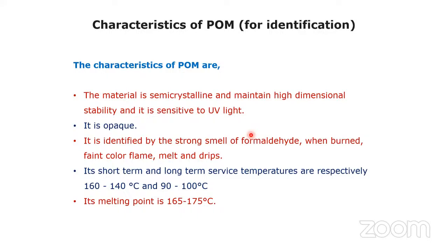Its short-term and long-term service temperatures are respectively 160 to 140 degrees Celsius and 90 to 100 degrees Celsius. Whatever the application temperatures, we can use it up to 160 for short term, and for long-term use you can use it at 100 degrees Celsius as well. Its melting point is nearly 165 to 175 degrees Celsius.